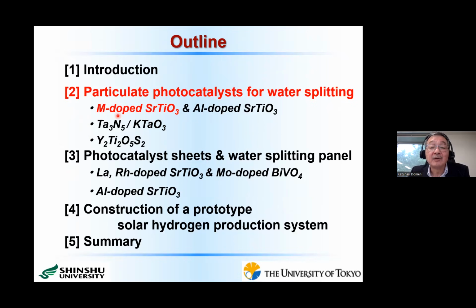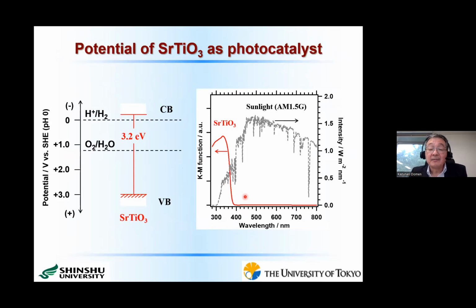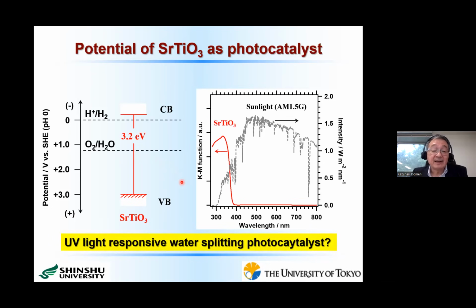At first, the metal doped strontium titanate. Probably, as you know, strontium titanate is a white colored powder, so this material's absorption edge is located at about 380 nanometers, so it can absorb only UV light, and can use only a small portion of sunlight. However, the band gap position of this material is suitable to split water into hydrogen and oxygen. So this material has the potential to be a UV light responsive water splitting photocatalyst.